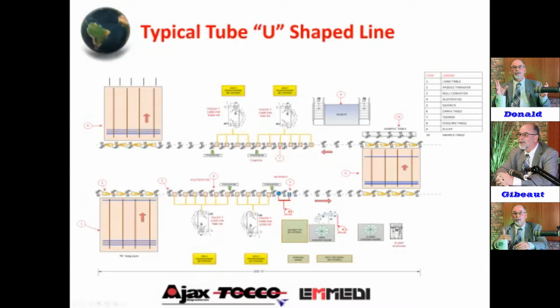And then we can take that pipe and build a buffer on this line, open a gap with the controls, and put that back on so that it can be run through the temper. And again, the temper is primarily below the magnetic Curie point. So we try to make the power supplies the same frequency for redundancy in parts, and it works out very well. And we've got great simulation software that allows us to do that. So it goes through the temper, comes out hot, most times 1,000 degrees to 1,250 degrees. And we talked about a 0.3 carbon typically is going to be around 1,300 for the magnetic Curie point. So this is all below Curie heating. Then we offload it with paddles onto the drag chain cooling table. So that is a typical U-shaped configuration.